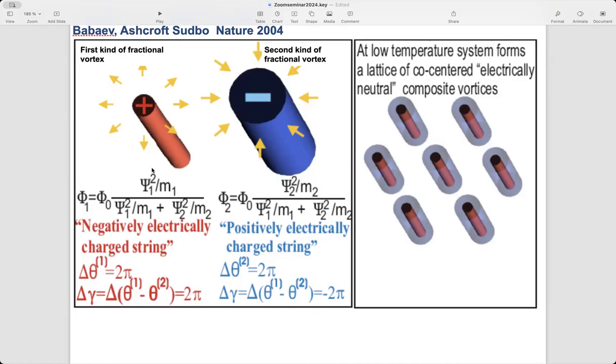And if one would form winding in only one condensate, let's say electronic, then such a vortex would carry logarithmically divergent energy and carry only a fraction of the flux quantum. Correspondingly, if you have an existing protonic condensate, you wind the phase there, and that would also carry a fraction of the flux quantum and also have logarithmically divergent energy, but they will attract each other, as they interact with a Coulomb force, a two-dimensional Coulomb force, so basically they tend to form these composite objects.